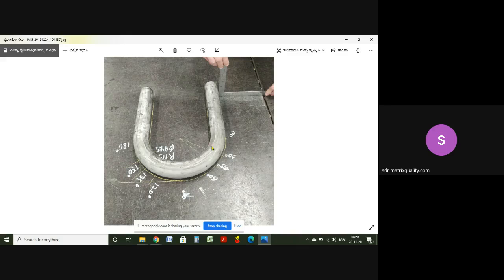After bending, we also make sections. That is the reason we put here 0, 30, 45, 60. This is a code requirement. So in these areas, we have to cut the tube and check the ovality. When we make the tube bending, the tube diameter cross section will not be the same all around. Because we are stretching, the uniformity cannot be exactly as a raw material tube before bending. So we will check how much ovality there is.